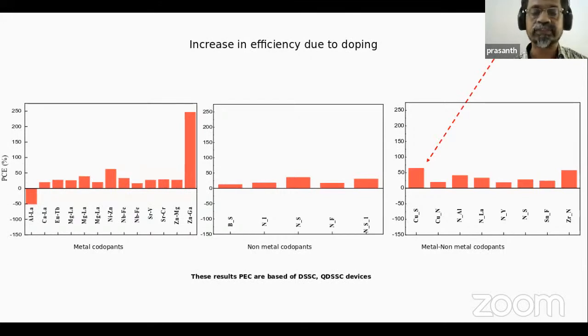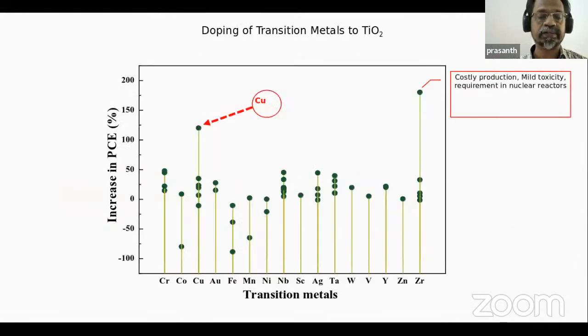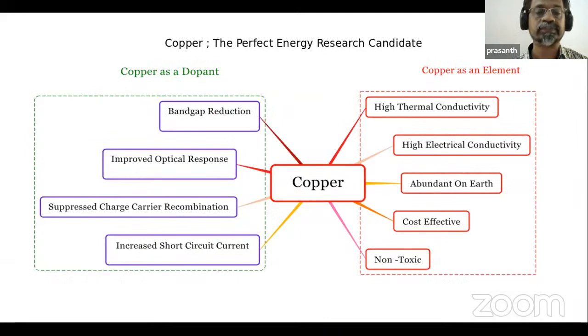So that needs extensive research in this area, and copper doped structures are showing a better effect in this way. That is making a very high incident photon to current conversion efficiency. That means the effect of copper in this structure is that it's making a band gap reduction by making interstitial energy band structures and improved optical responses, suppressed charge carrier recombination and increased short circuit current, and high thermal conductivity, high electrical conductivity, and cost effectiveness and non-toxic nature.